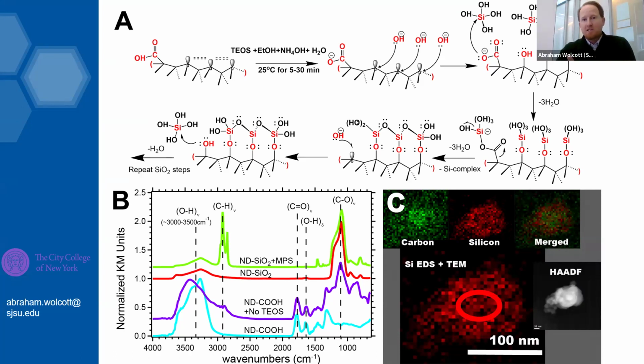And who knows, maybe even if we did TEM, I mean, this would be a paper: take the silica, do TEM, then do the annealing steps at 100, 200, 300, 400, redo your TEM study, and do you begin to see crystallographic orientation of SiO2? Yeah, it would be a very interesting experiment, and then to check also robustness, shelf life, and everything. Yeah, and again from practical perspectives, exactly. And then you could do a dissolution study: after doing an annealing step at 300 C, we put them in water for 2 months and didn't see any change. The silica remained robust. We didn't have any issues with the thinning of the shells, and so on and so forth.